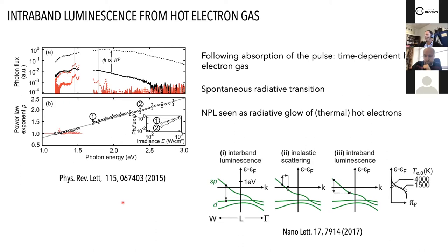And one of the hallmarks of this effect is exactly what's specified in this graph here on the left panel. So they took spectra, this is the log scale, and they look at the evolution of the spectrum with laser power for each energy inside the spectrum. Then they have this nonlinear order dependence as a function of wavelength. And this power law exponent is now plotted in the bottom graph as a function of the photon energy. And what they saw is remarkable.